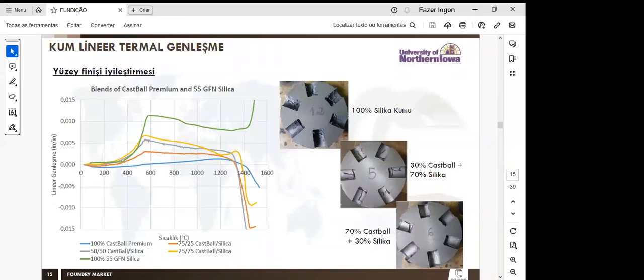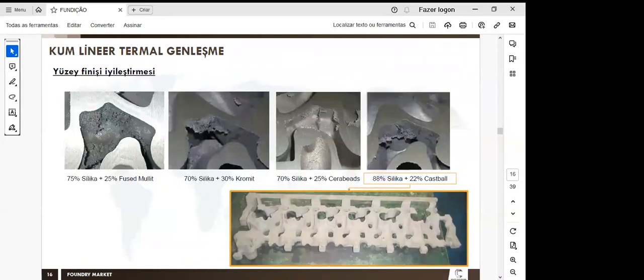We can see the results when we add Castball into a mix with silica sand. We can improve the surface finish of the castings. This example is with iron casting. We can see the thermal expansion is reducing, as are the veining defects and penetration defects. Next, we have real examples of improvements in the surface finish of casting parts.